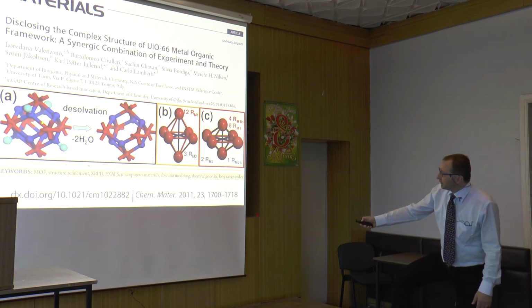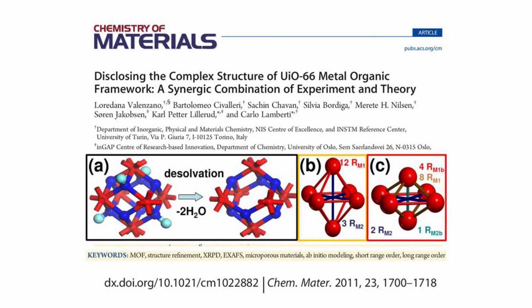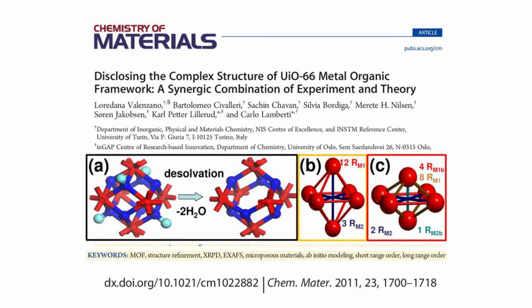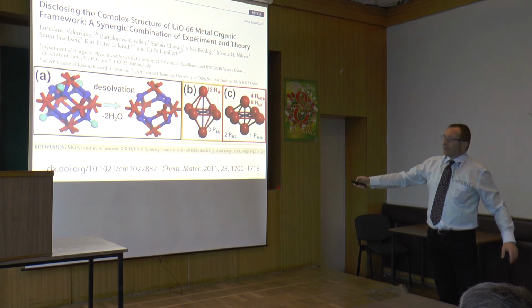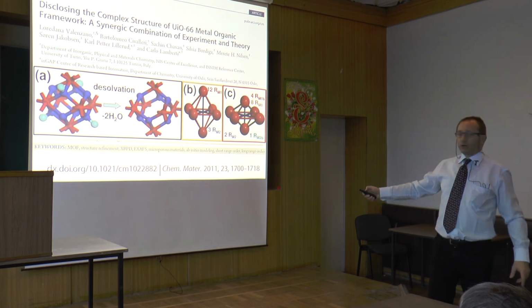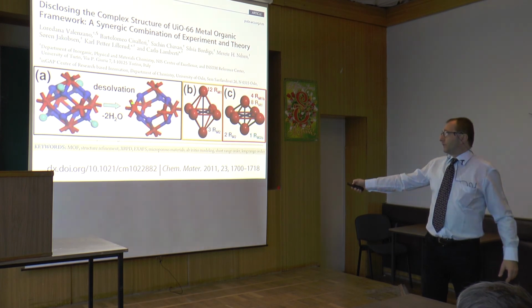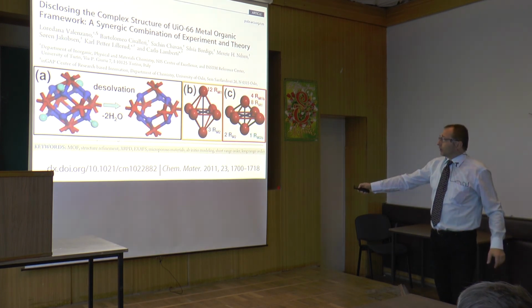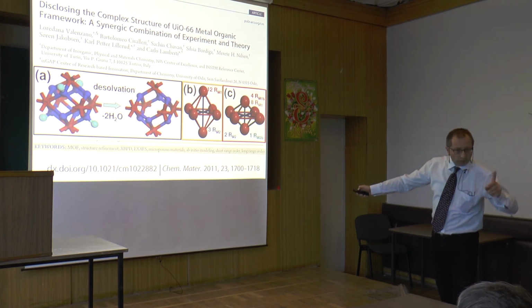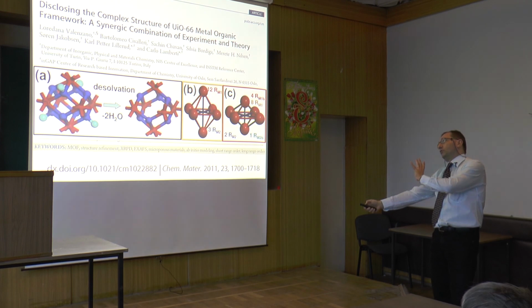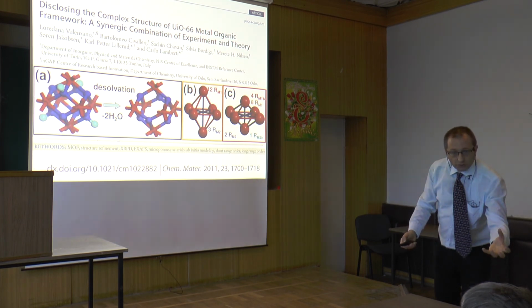So what happens is that we have, imagine an octahedron. An octahedron has 8 triangular faces, right? 4 in the bottom and 4 in the upper part. In 4 of these 8 faces you have a mu3 oxygen that is bridged with 3 zirconium, and in the other half of these faces you have an OH group. And when you make the desolvation, you remove the solvent, but you also remove 2 framework water molecules. So this goes out as 2 water molecules, but before, there were framework oxygens.